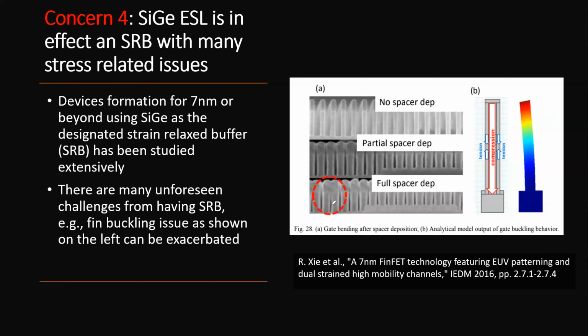The transistor here is dead because you cannot have the work function coming in and do what it's supposed to do. So this is what they studied, and they have to optimize the process to avoid this gate buckling or fin tilting issue. These are stress-related issues, and they come from the SiGe layer below it. The fin buckling issue can be exacerbated. That's a problem, and people found out you can solve the problem for sure, but it's not as easy as you saw here. Your process needs to change. I think that's the bottom line.